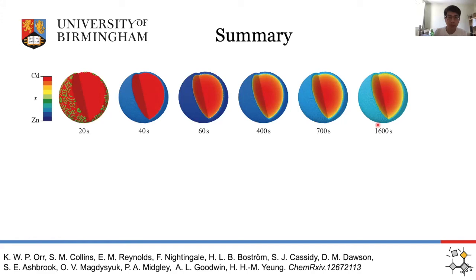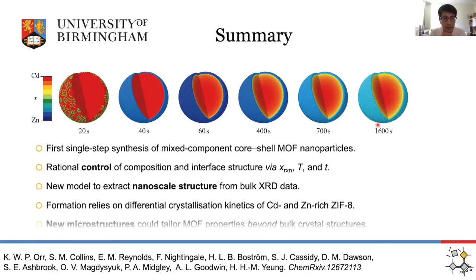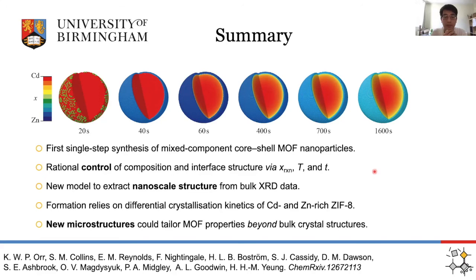Reaching the end of my talk, here's the summary. We've discovered essentially the first single-step synthesis of demonstrably core-shell MOF nanoparticles with mixed components, and been able to control their composition through synthesis parameters — composition, temperature, and time. We've also developed a new model to extract structural information at the nanoscale from bulk X-ray diffraction data, underpinned by transmission electron microscope images. The in-situ diffraction tells us this formation relies on differences in the crystallization kinetics of the cadmium-rich and zinc-rich metal-organic frameworks. Looking ahead, if we can understand crystallization better and form new microstructures, we can tailor MOF properties beyond the bulk average crystal structure.